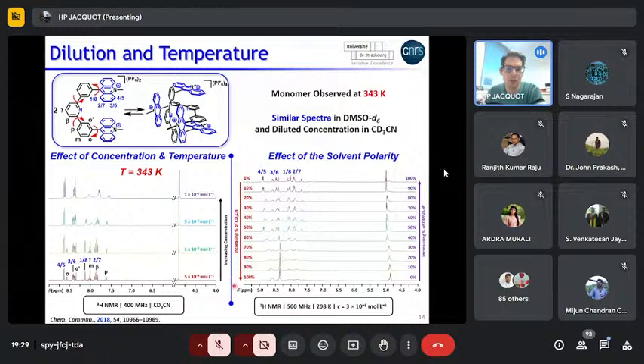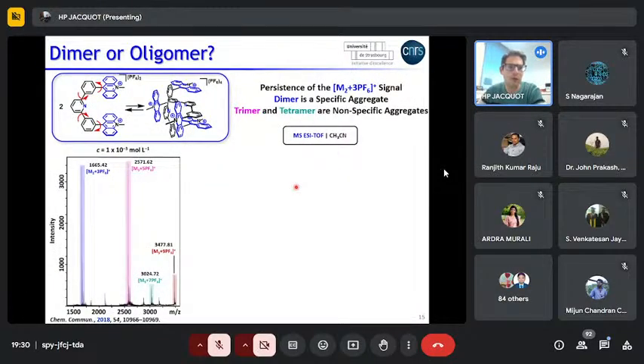Also, this equilibrium was confirmed by a solvent polarity study. So when we have 100% of acetonitrile, we have a broad spectrum. And upon addition of DMSO and going into pure DMSO, we end up with the spectrum of the monomer, which is expected because DMSO is a competitive solvent. So one proof that we have this dimer in an organic medium was provided by mass spectrometry.